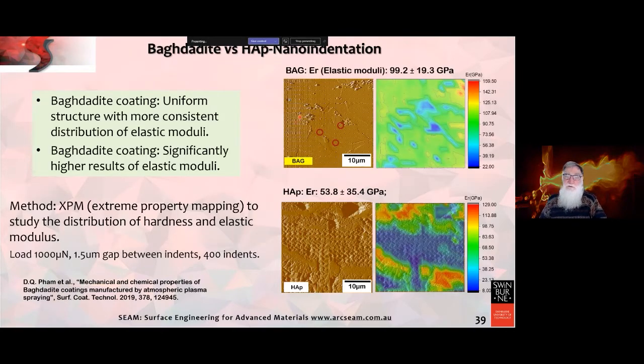So we've been measuring the mechanical properties. So baghdadite versus hydroxyapatite versus nanoindentation. Now you may not be able to see these very small indents, but there's a whole raster. Bang, bang, bang, bang, and three of them are circled. They're a lot easier to see with the hydroxyapatite. But all of these nano indents have been applied in a raster across the cross section of a baghdadite coating and a hydroxyapatite coating. And by using software, you're able to establish a map